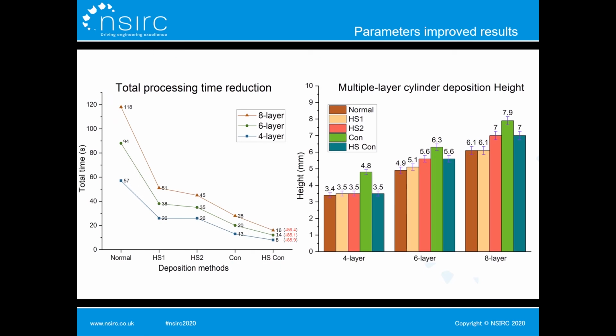And this slide shows the results comparison of different cylinder deposition methods. At left is the processing time chart. We can see, from initial normal to high speed, then finally to the continuous spiral deposition method, the time cost is gradually and sharply decreased. All the multiple depositions which applied the HS continuous spiral method save around 85% time compared to the normal method.